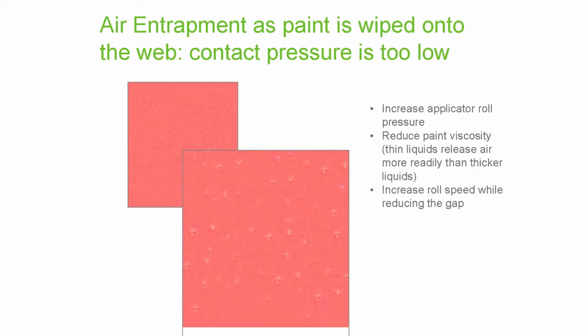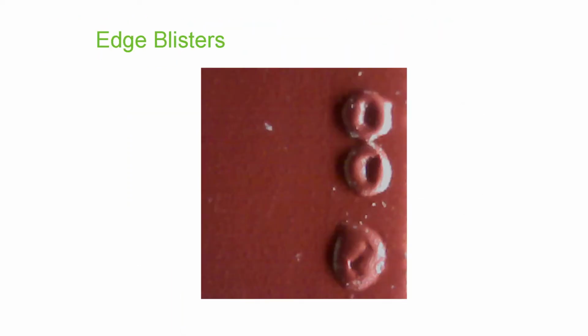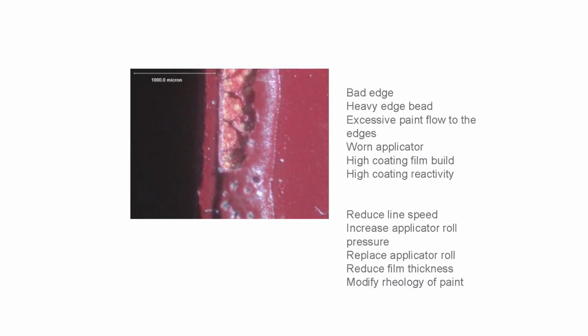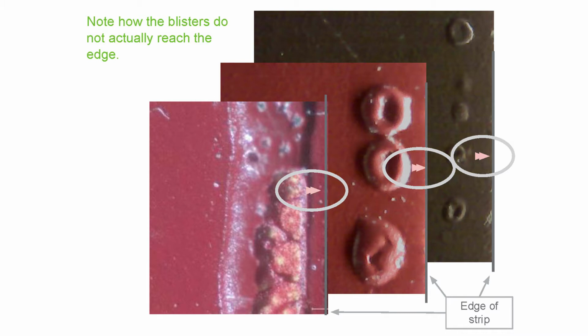What does happen, though, and let me just get right to it, are edge blisters. Now, I don't know that you have a problem like this here in Europe, but a typical coil bake in the US is about 15 seconds. So these blisters are forming right on the edge, and they're forming on the edge because there's a bead that's developed. And we've probably debated for 15 or 20 years why that bead is there in the first place. And I've got multiple pictures of this. And the bead is always the same. There's always an area that's relatively flat and no blisters, and then you form blisters.